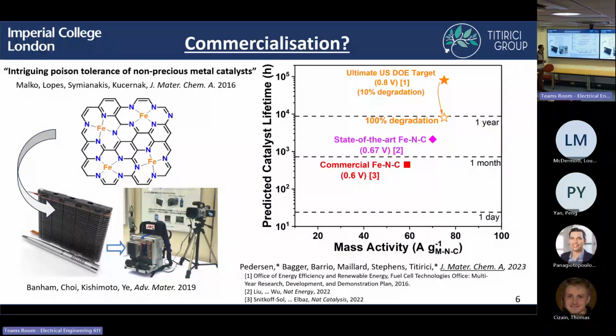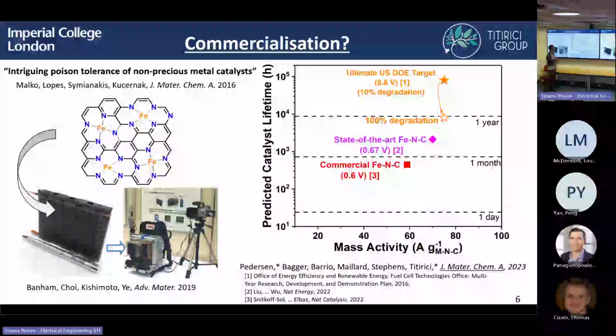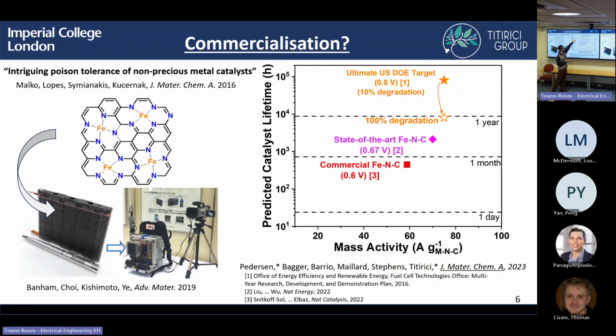But ideally, what we want to do is really scale up this technology and use it in, say, transport applications. In those scenarios, you really need to consider a really long lifetime of your catalyst. So you see in the top right here, this is the ultimate US Department of Energy target. This is running for, say, 5 years, and ideally, over that time, you want just around 10% degradation of your catalyst. Just for comparison, a state-of-the-art iron, nitrogen, carbon catalyst can operate for several months, but this is with 100% degradation of the catalyst. So we're still over an order of magnitude off where we need to be if we want to use it in, say, transport applications in a car.